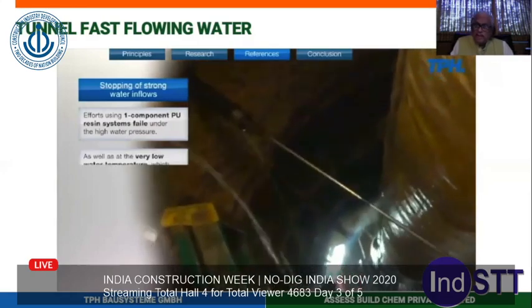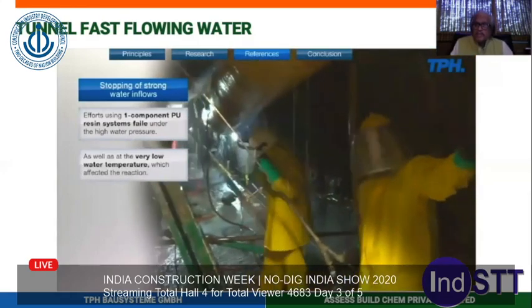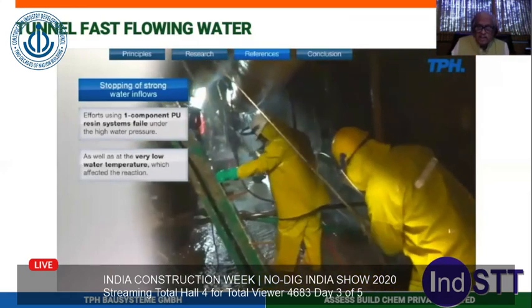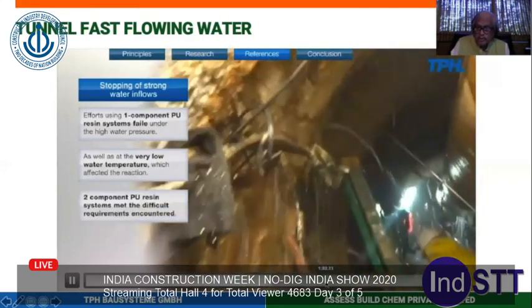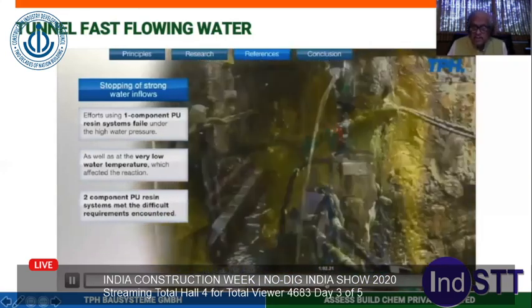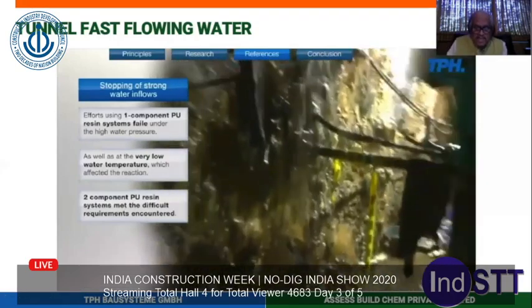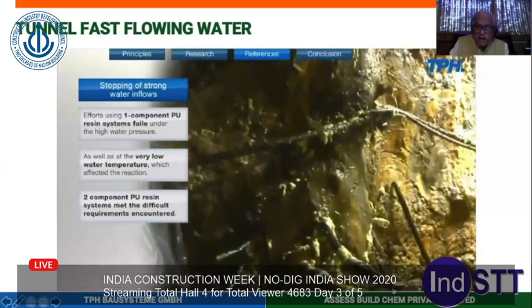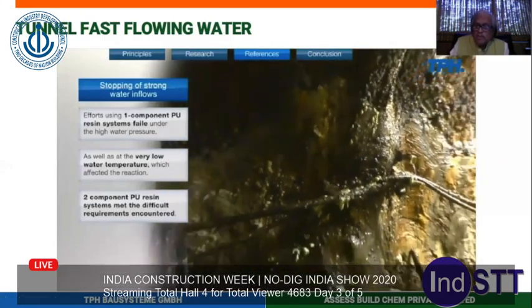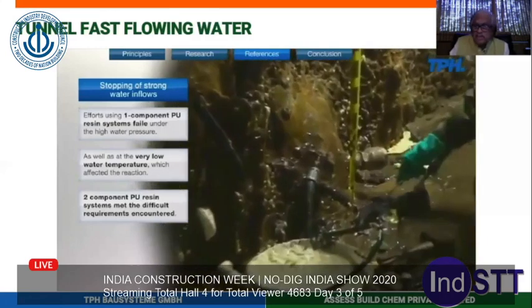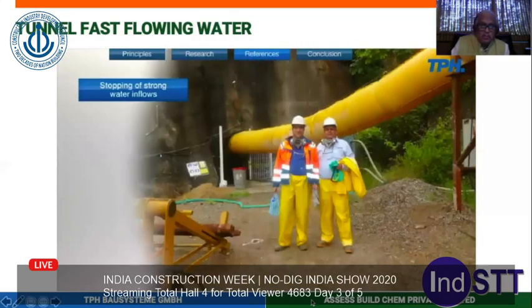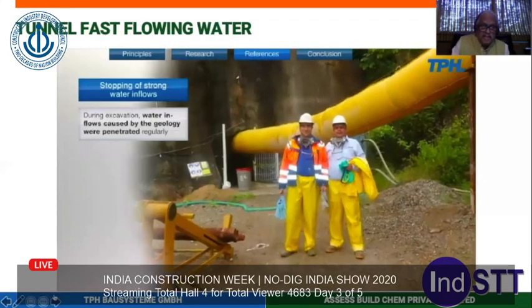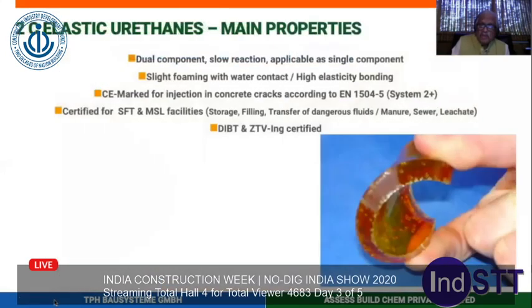So primarily, you will have to go in for two component injections, because two component injections have controlled reactions. They are a little bit harder compared to one component. The foaming capacity is less, maybe up to 14 or 15. So they can really stop this water when you use proper machinery to push these materials inside. So this is how from a one component material you become a two component material.